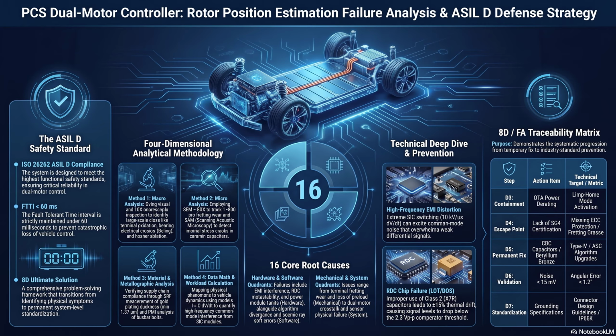Unbelievable. Okay, what about the missing phosphate coating on the busbar bolts? This ties back to the PMI testing. How does a microscopic surface treatment dictate torque? Well, it dictates the relationship between torque and clamping force, and those two are not the same thing. Okay, break that down for me. So the torque applied by the factory automated screwdrivers is governed by a specific equation. Torque equals the K-factor times the nominal diameter times the target clamping force. And the K-factor represents the friction coefficient of the threads.